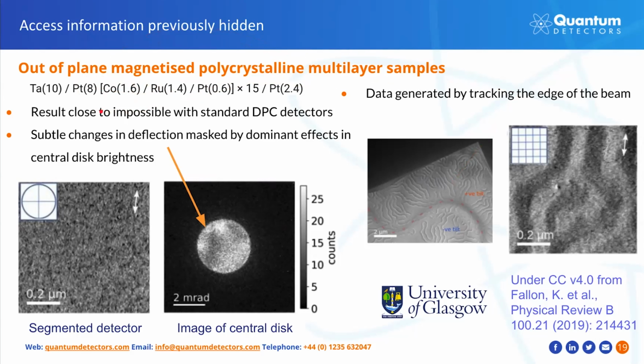So let's try to use our standard detection. Once we deploy the conventional segmented detector, the signal is totally overcome by the contributions from the diffraction contrast, and this can be simply visualized here. What we are after is small changes in X and Y positions of this probe. However, when we scan over a sample like this, the intensity inside of the disk redistributes, and this is read out as additional deflections and masks the magnetic contrast.